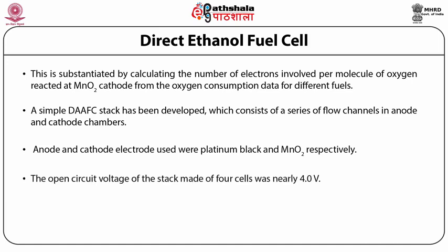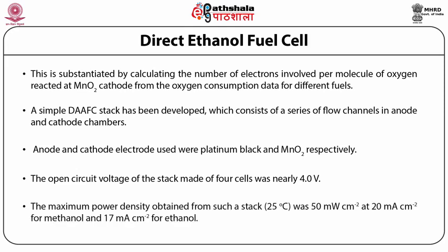The open circuit voltage of the stack made up of 4 cells was nearly 4.0 volts, and the maximum power density obtained from such a stack at 25 degrees Celsius was 50 milliwatt per centimeter square, at 20 milliampere per centimeter square for methanol and 17 milliampere per centimeter square for ethanol.